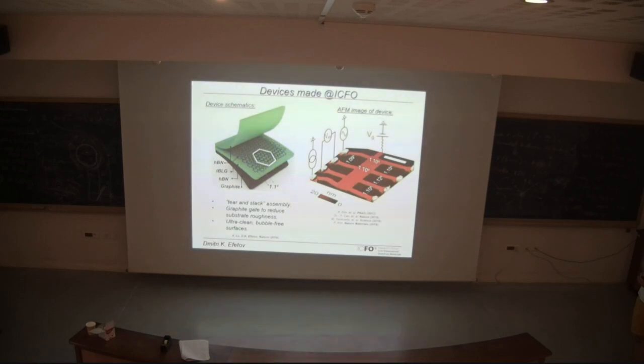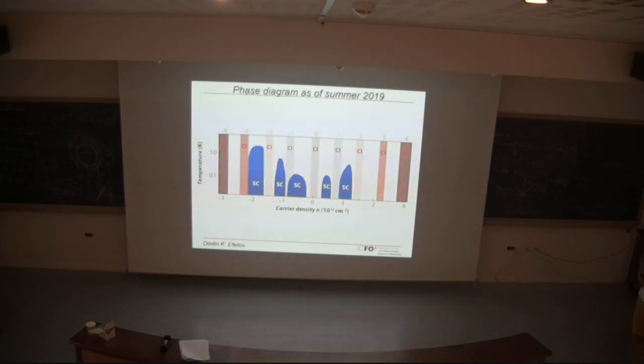So bottom line, I think the reason we now started observing other insulating states in the superconducting pockets is that we can now resolve in transport much smaller gaps, which in more disordered devices are just washed out by these imperfections.